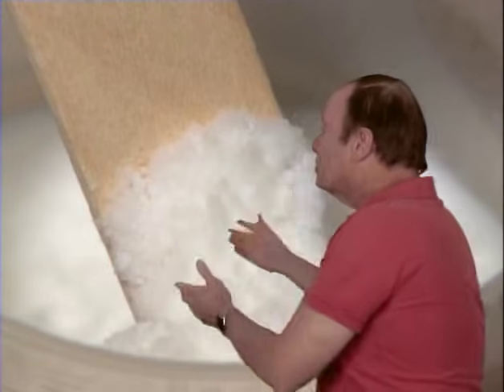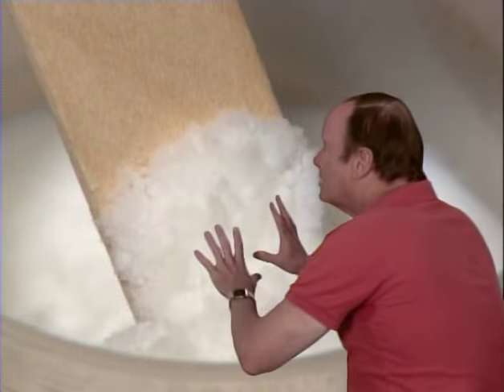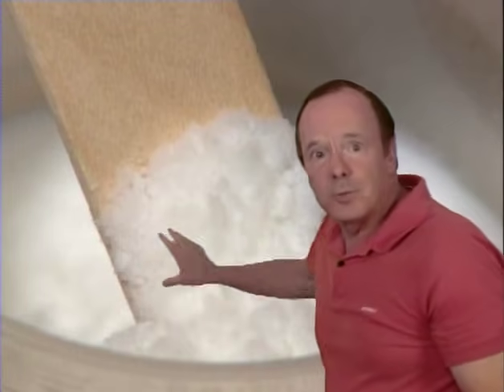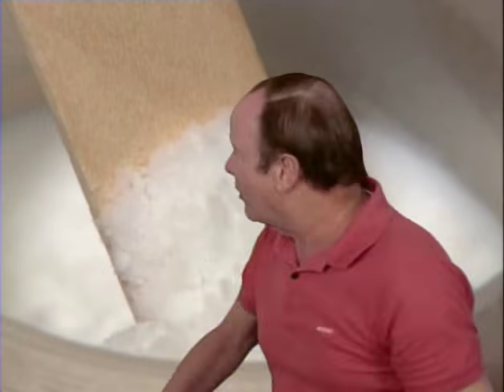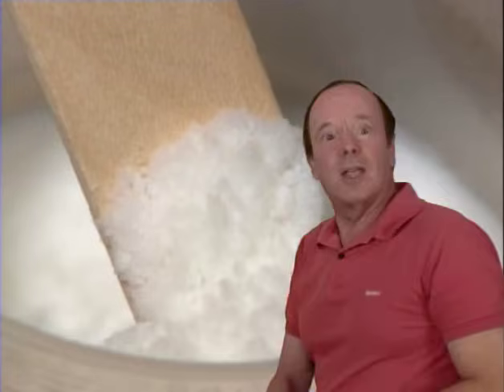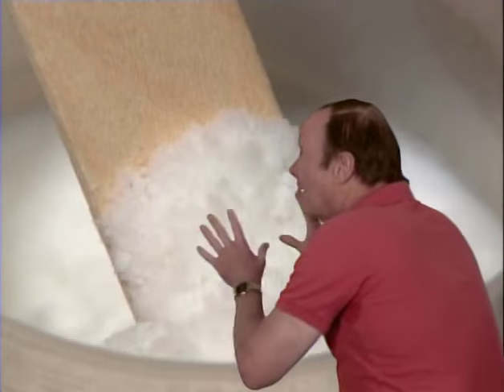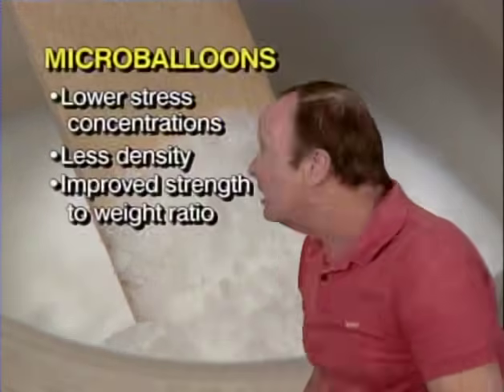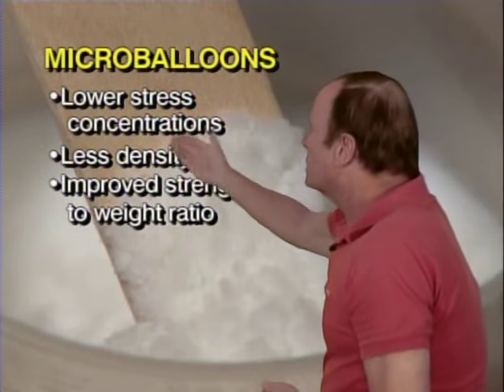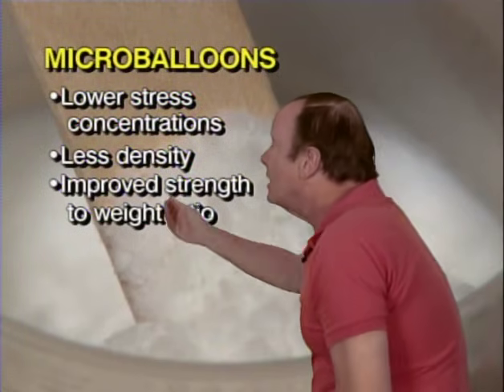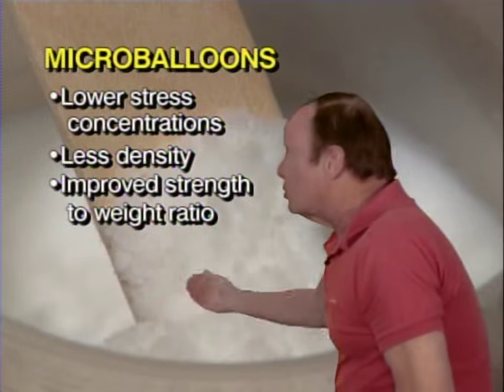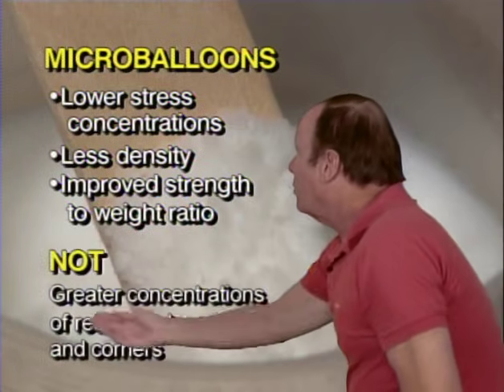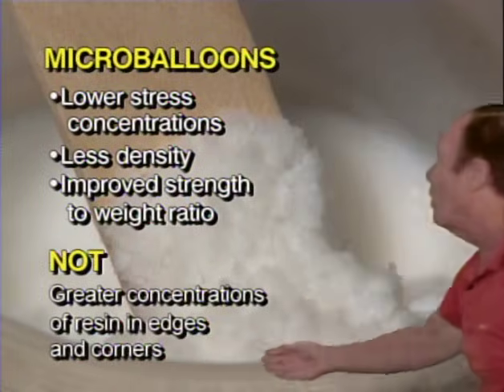So microballoons also, by the way, make the resin mixture less dense, and that reduces the weight and improves the strength to weight ratio. Now, the FAA might ask you if a benefit from using microballoons is that you might get greater concentrations of resins in the edges and corners of the repair, and the answer is no, you get less concentration of resin, and that is a good thing. So what are the good things? Well, microballoons lower stress concentrations, they give you less density, they give you improved strength to weight ratio, but what they do not do is give you greater concentrations of resin in the edges and corners.